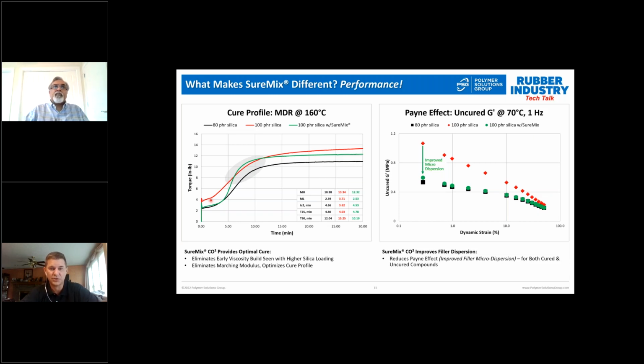When you use SureMix, what you can see in the green curve, you see the type of step that you like to see with a sulfenamide cure. You see a low viscosity, a fast increase, and then a plateau. And this happens because SureMix actually has a higher affinity for the silica surface than the accelerators do. So SureMix is able to outcompete this for the silica surface and keeps the accelerators in the rubber, in the compound bulk, cross-linking the compound.